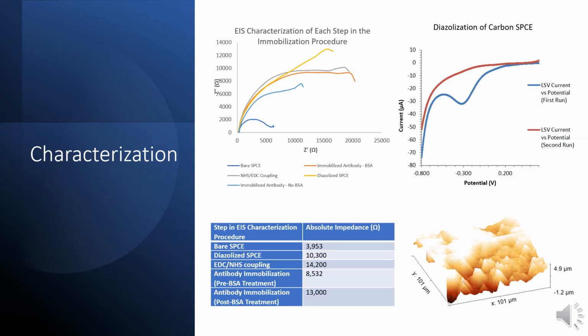I am currently working on characterizing the screen-printed electrodes. The figure in the top right verifies that the working electrode is being properly immobilized with the diazonium salt during the first LSV scan, due to the peak seen at minus 0.3 volts. The absence of this peak in subsequent scans indicates that the reaction has run to completion.